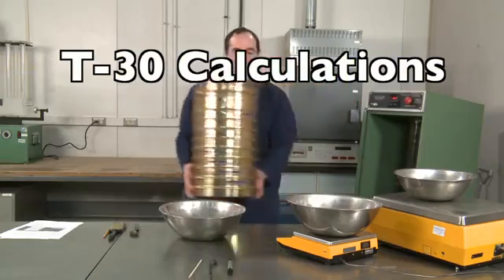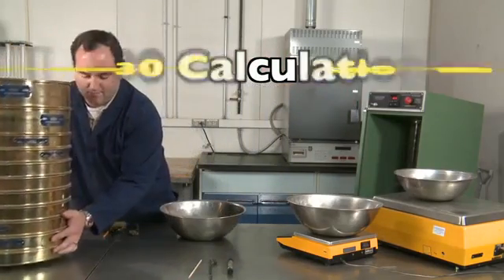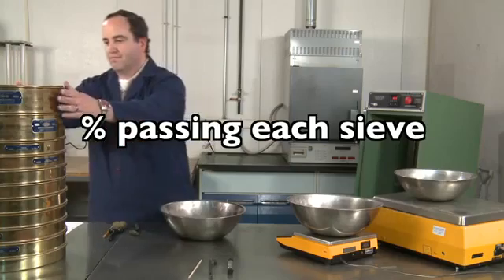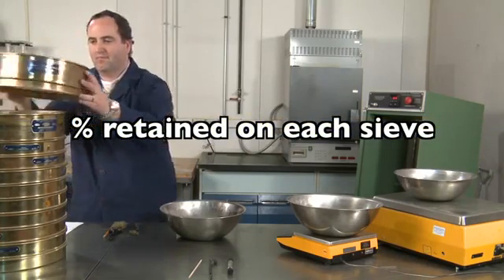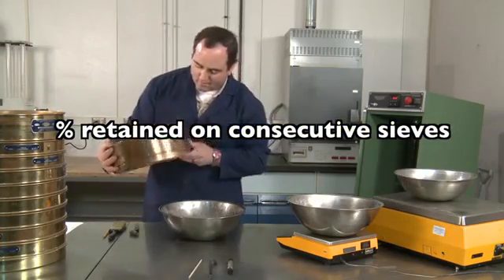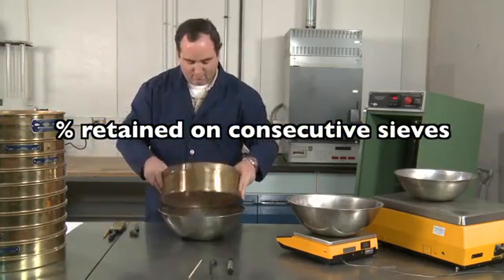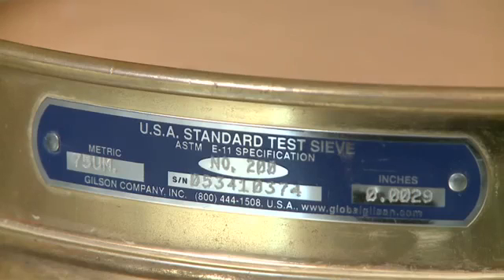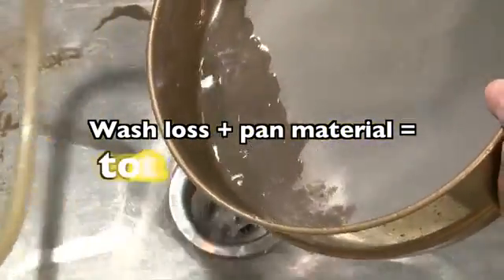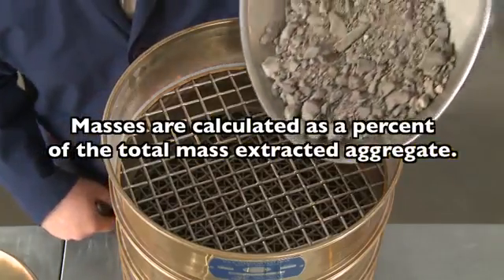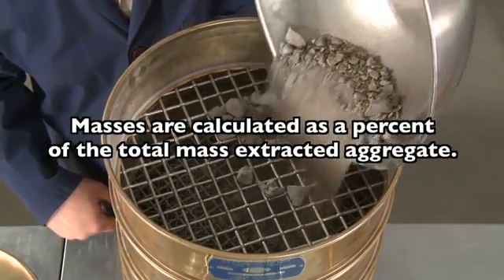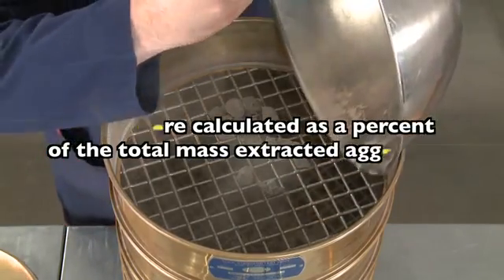Depending on the specification, sieve analysis calculations may include the total percentage of material passing each sieve, or the total percentage of material retained on each sieve, or the percentage of material retained between consecutive sieves. The mass of the material passing the number 200 sieve must be combined with the mass of the wash loss to obtain the total percentage of minus 200 material. Convert all recorded masses to a percentage of the original dry mass of the extracted aggregate.